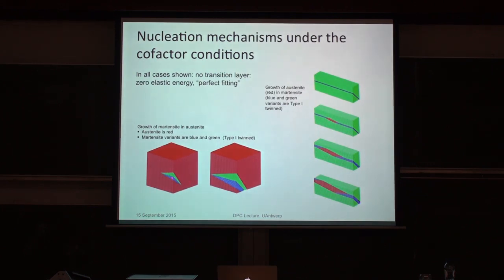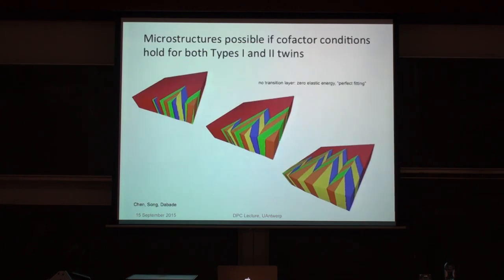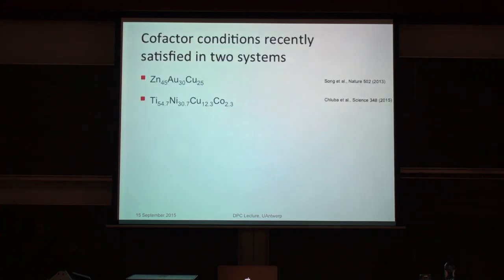And again, these are nucleation mechanisms. This is nucleation of the martensite in the austenite on a corner. This is nucleation. This is two martensite variants, a blue and a green one. And it's nucleation on a band. Again, these are zero energy microstructures. Here's something even more complex if you satisfy it for two different twin systems. Again, a kind of jigsaw puzzle type situation that you can move in. So very recently, two alloy systems have been discovered which satisfy those conditions. Our paper was first, actually, but this is the real spectacular result.